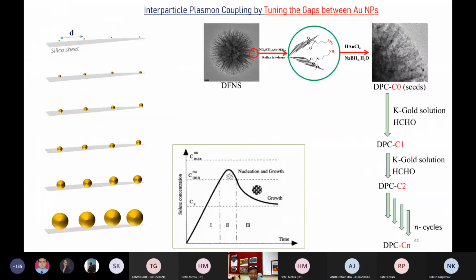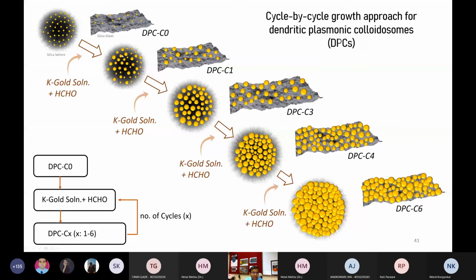So we decided to make that, and we used this cycle by cycle approach, where we first took a silica loaded with the gold seed, then we added another batch of a gold precursor in this first cycle, third cycle, fourth cycle, and you see now the gold particles are coming closer and closer. We don't know what is the best distance between the gold nanoparticles that will allow us to absorb broadband light.